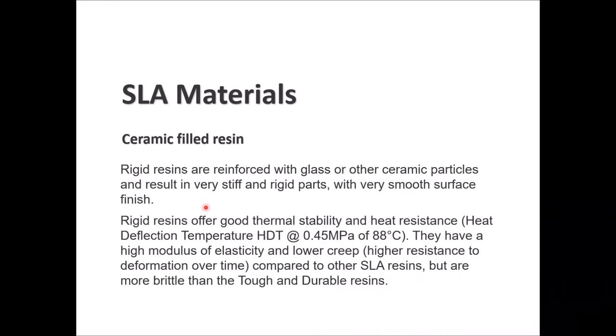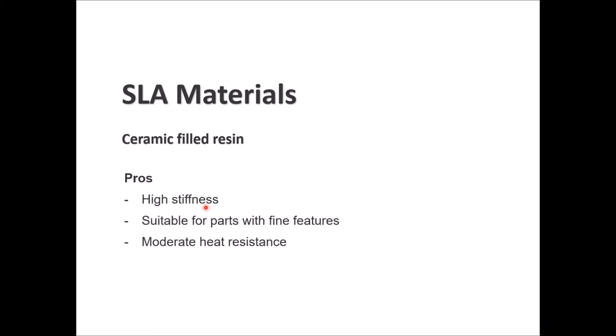Ceramic-filled resins are reinforced with glass or other ceramic particles, giving very stiff and rigid parts with smooth surface finish. They offer thermal stability with a heat deflection temperature of up to 88 degrees Celsius at 0.45 MPa, high modulus of elasticity, and lower creep — meaning high resistance to deformation over time. However, they are more brittle than tough and durable resins. The right material always depends on your specific application.